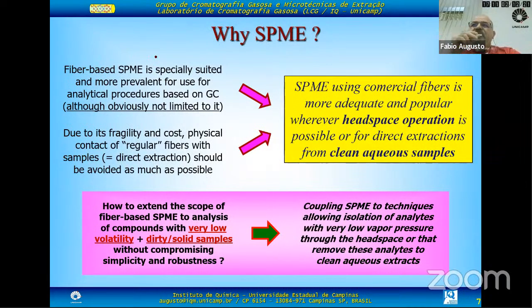Well, the problem is that fiber-based solid phase microextraction is more suited for GC due to its characteristics. You can use it for direct mass spectrometry, for LC, for lots of different sample preparation techniques, but it's much more suitable for GC. And the fibers are very fragile, and they are very, very expensive. A box with 3 fibers costs $250, $300 in the US. In Brazil, for example, they cost 10 times more. I believe in Argentina it's pretty much the same because you have the importation costs, the taxes and so forth. So they are very expensive. It's too much money for such a delicate thing.